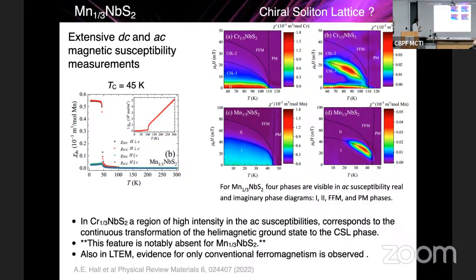But since making these measurements, we've also had time to look at the manganese material, with crystals and powder, using neutron diffraction. And we find that there may be some interesting structural properties that may indicate some sort of modulation in the ferromagnetic structure. And if we were to look at slightly larger lamellae with the microscopy, we may be able to distinguish very clearly whether it's really a ferromagnetic state or a highly ferromagnetic chiral soliton lattice.